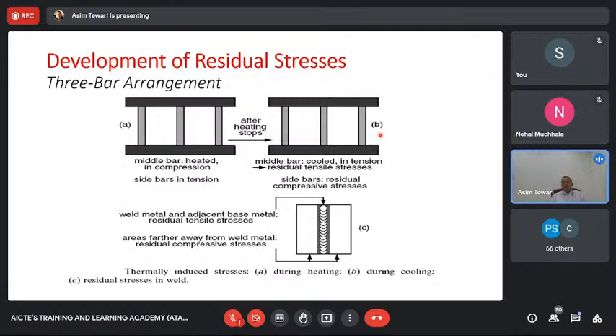What we are doing now is that we are going to cool it down. When we cool it down, the liquid in the central rod will now freeze and solidify. Till it is liquid, it is all right. But once it freezes, it can now again start exerting stresses. But now what you realize is that the liquid from the central rod has flown away when it expanded and more got molten. And now once it is being frozen, it's probably having much less material. And thus once it is frozen, it shrinks. And that shrinking is more than what the expansion actually was. And that is because it has less material now and it is shrinking.